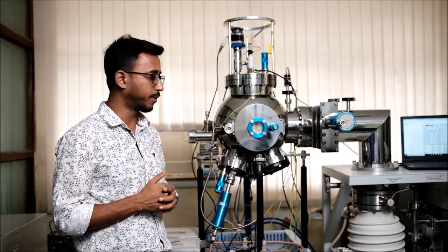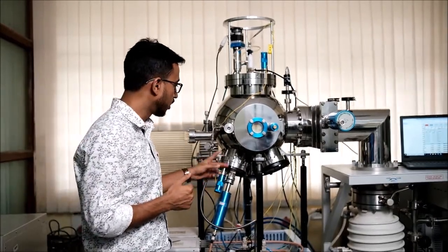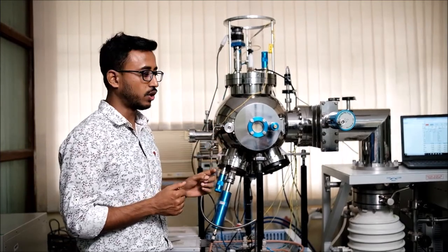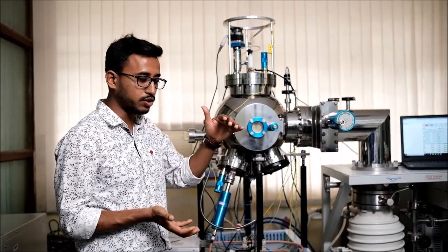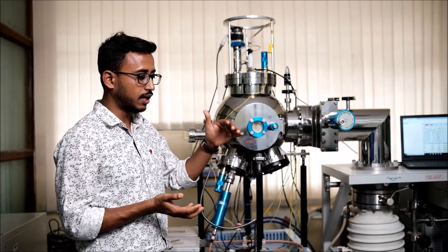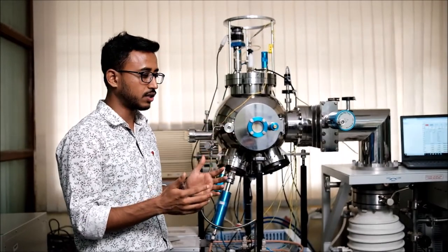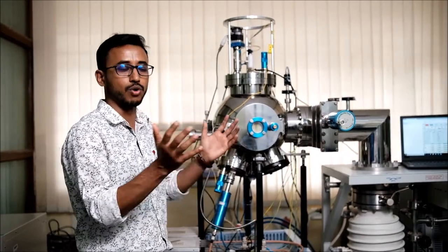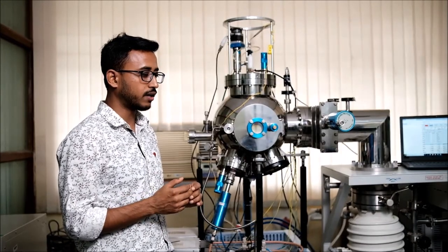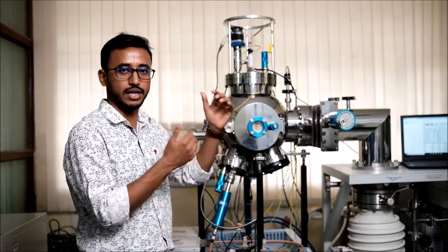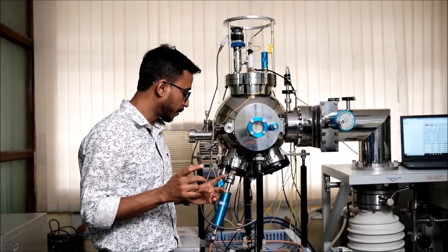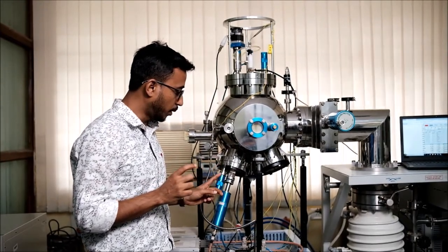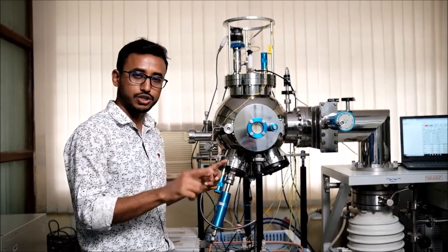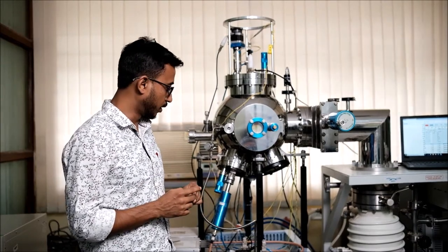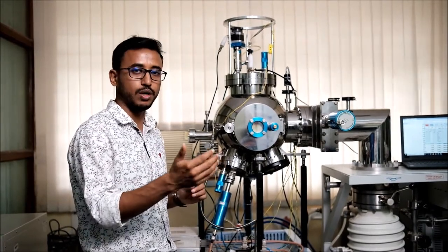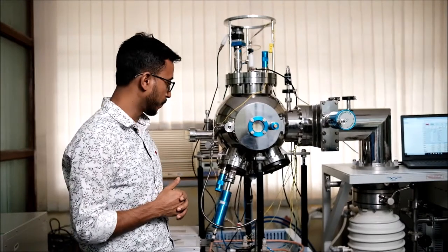Then the most important parameter is also the target to substrate distance. As we reduce the target to substrate distance, the deposition rate increases because it does not scatter more. So we can set a distance accordingly as we wish. And also we have to take care of the argon to oxygen ratio, because more oxygen will make it more oxide filled.